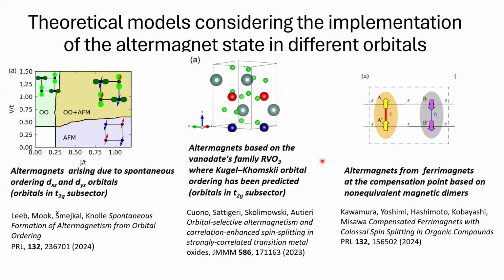Kugel-Khomskii orbital ordering. And it has been predicted that such ordering will give altermagnet properties. So here we also have orbital ordering, in this case in the t2g subsector. And a very interesting suggestion also appears for the creation of altermagnets from ferrimagnets, which are at the compensation point.